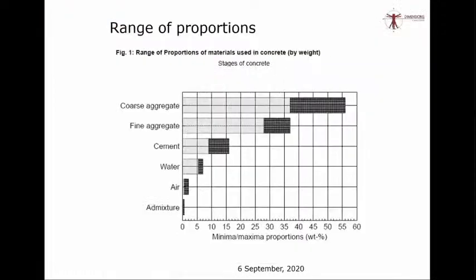The same table is expressed in a graphical form. Don't take the absolute values for your references. It is only a relative thing that you should see, because nowadays concrete mixes are done in fantastically different environments. You have different ranges of concrete, so these proportions will not be applicable to any concrete which you take, but it is generally so. For example, this graph represents coarse aggregate content somewhere around 35 or 36 percent to 55-56 percent. You cannot fix these numbers, because for the same grade the mix proportions from area to area, from source to source of the aggregate will vary. So this is only a relative representation.